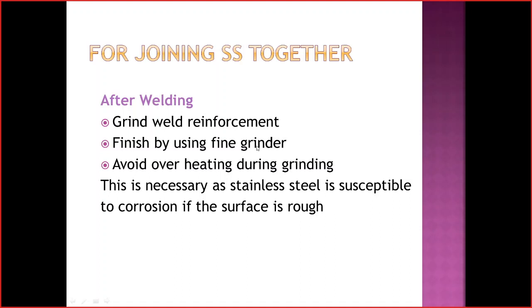Once you use a grinder for stainless steel, it should be dedicated to stainless steel bodies only. Remember, otherwise it will cause chromium loss. So whatever grinders you are using for surface cleaning must be dedicated to stainless steel only. And avoid overheating during grinding. This is necessary as stainless steel is susceptible to corrosion if the surface is rough. Remember.